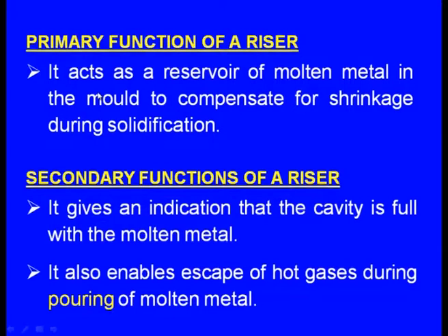Now, let us see what is the primary function of a riser. It acts as a reservoir of the molten metal in the mould to compensate for the shrinkage during solidification. We all know that all the metals, when they solidify from the liquid state, undergo shrinkage. This is known as the solidification shrinkage. Because of the solidification shrinkage, a shrinkage cavity will be there, and the molten metal which is inside the riser comes and fills that gap, and it compensates that gap.